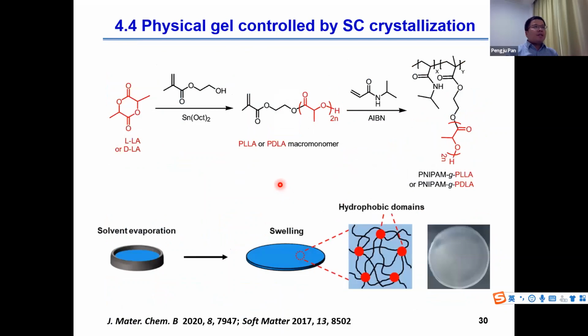Besides the polymer elastomer, stereocomplex crystallization can also be used to tune the physical properties of a physical gel. For this study, we prepared a physical gel based on an amphiphilic graft copolymer. This copolymer was synthesized by random copolymerization of PLLA and PDLA macromonomers and N-isopropylacrylamide. Then we changed the solvent to water and prepared the hydrogel film.